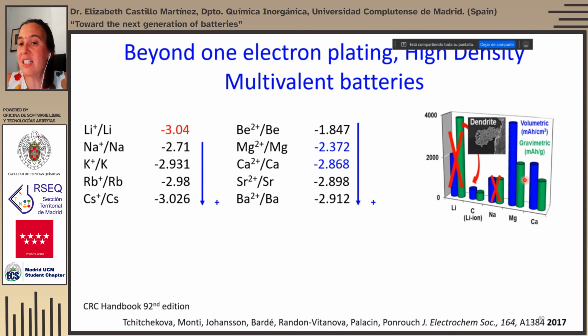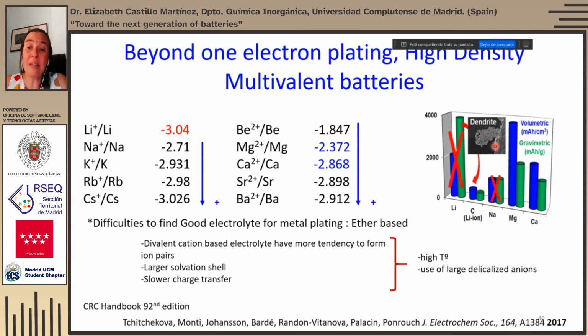batteries. An additional advantage is that when these metals are plated, dendrites are not formed. The main difficulty, however, is to find a good electrolyte that allows the plating, because we have cations with very large charge densities. I mean, we have a charge of +2. They tend to form ion pairs with their anions in the electrolyte, and also they tend to get very large solvations there. So it is quite complicated for the charge transfer to take place. So the strategies that are being used are to use high temperature, use large delocalized anions, as well as the use of ether-based solvents rather than carbonate solvents.